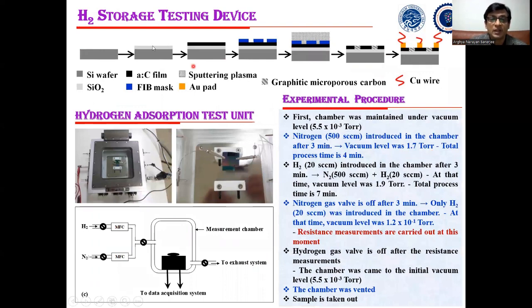And this is the fabrication technique by lithographic process for hydrogen storage testing devices. So we started with a silicon wafer, then deposited amorphous carbon, then using some masking, we sputter-deposited the graphitic microporous carbon network in some specific spaces, and then finally we packaged the device. And this is the device structure, and this is the experimental procedure and experimental schematic.